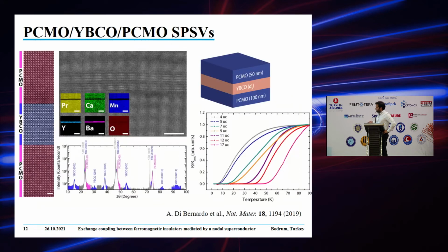So I started to grow these trilayers of PCMO, YBCO, PCMO. Now the two PCMO layers are chosen such that we are already at a thickness where there is no mismatch in coercivities of these two layers, so they are quite thick, as you can see. And the YBCO thickness is changed between, I think it was 17 unit cells, the thickest sample, down to 4 unit cells. So this was the smallest thickness for which I still observe superconductivity.